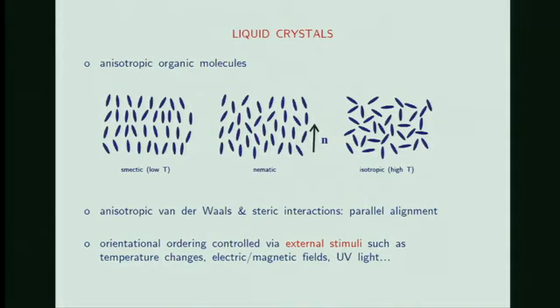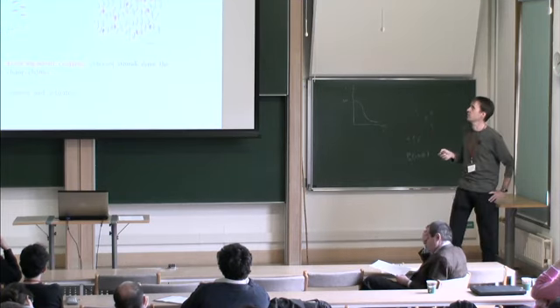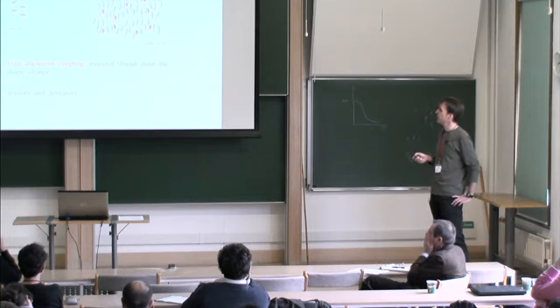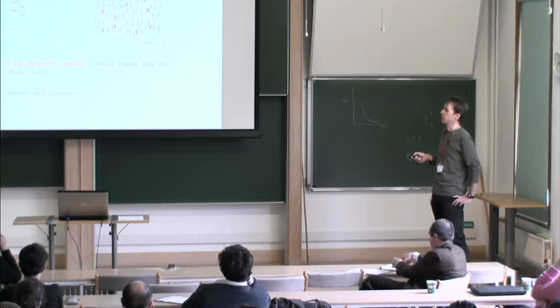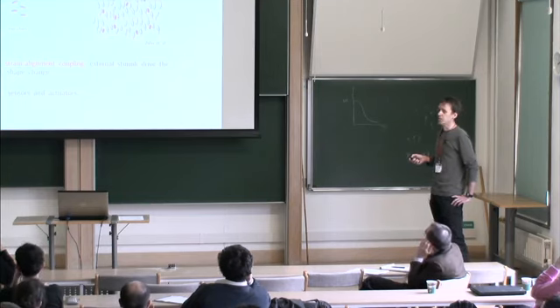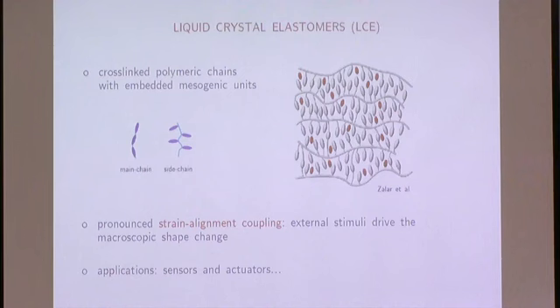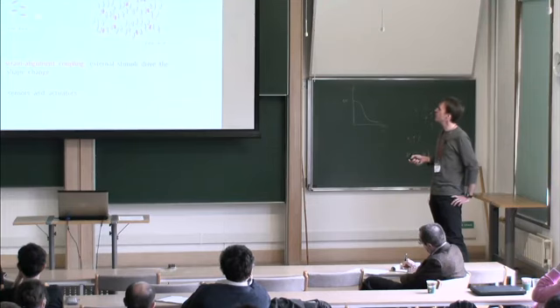Now joining these two types of materials gives you liquid crystal elastomers. Joining means that you have the polymeric chains, and then you embed your mesogenic units. This can be done in several ways. There are, let's say, two main types. You have so-called main chain materials, where the mesogens are part of the polymer backbone. But you can also have a flexible backbone with mesogens attached to it. In this case, you're dealing with so-called side chain elastomers, and there are different possibilities of how to attach them. This is a more artistic depiction of a side chain elastomer here.